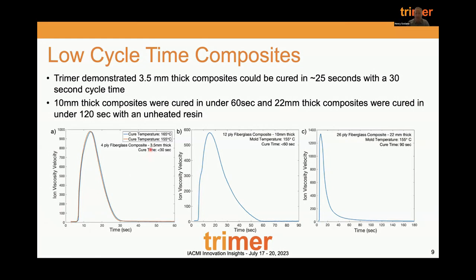This is a 3.5 millimeter thick fiberglass part with an unheated resin. So if you have a preheated resin and you're doing RTM or HPRTM, it can go faster. Really very, very quick material. So what we did is we've done some thicker components. This is showing a 10 millimeter thick composite. It was cured in about 60 seconds, and this one is a little thicker, and it's curing in about 90 seconds. So really very fast, potentially too fast for some applications.